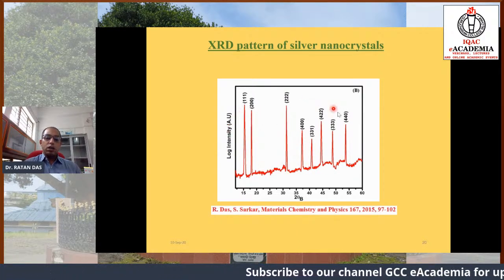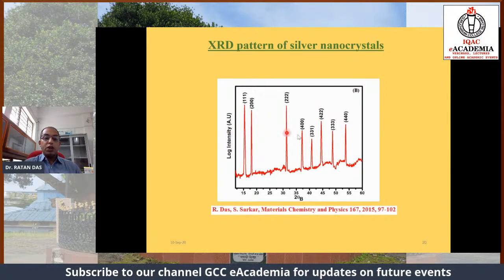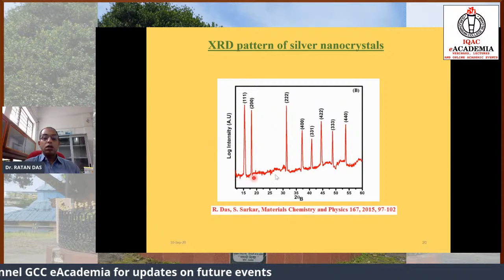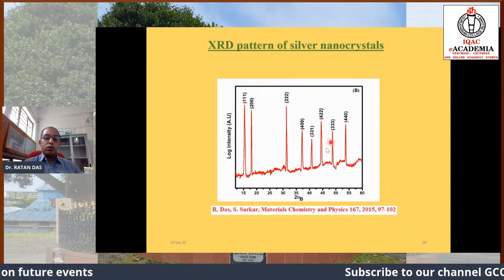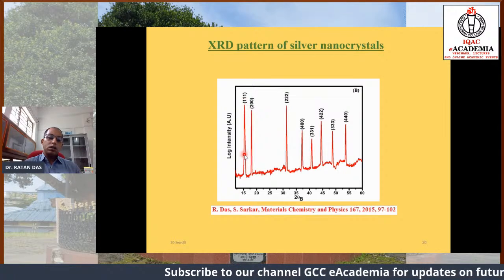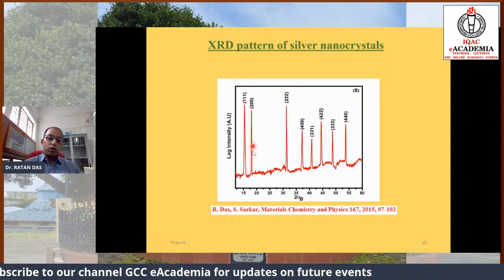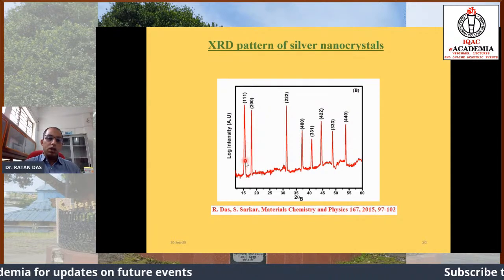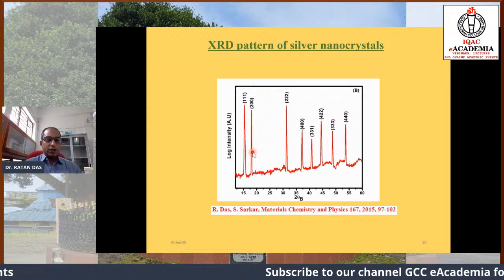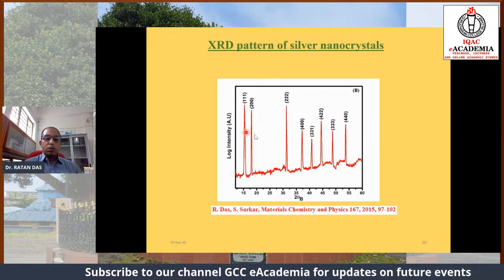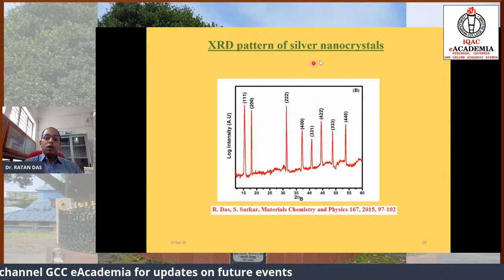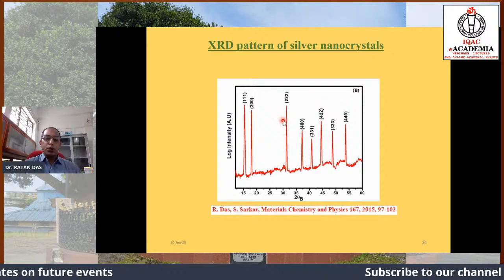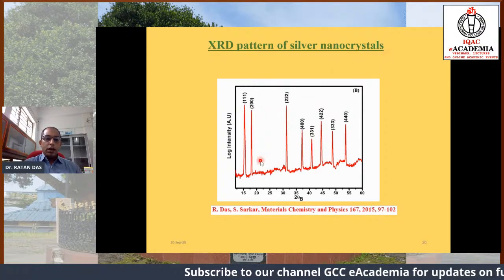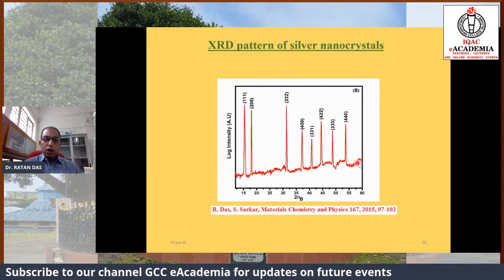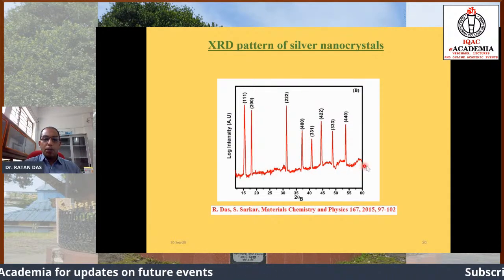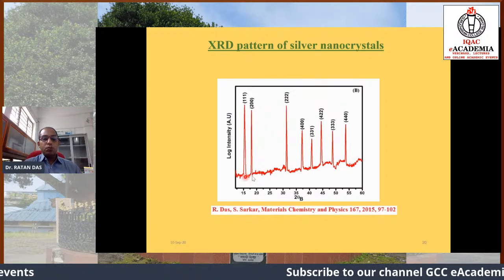You see, in the X-ray diffraction pattern, we have obtained various peaks in the sample. So many peaks are available. And among the peaks, you see one peak is very narrow in width, but another peak is showing some width. This width is very important for researchers like us. This particular pattern shows that the silver nanoparticle that we have prepared is crystalline in nature. Another thing I want to say is that below this particular pattern is the background pattern, and this is also very important, because you have to know the background pattern.